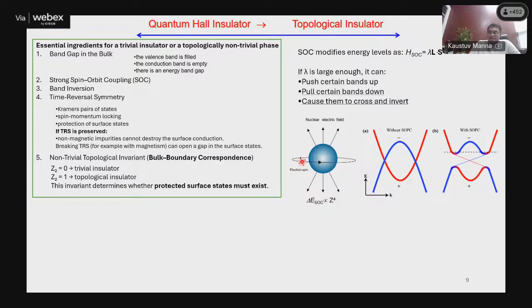So in case of Z very high, in the rest frame of the electron, what you see is that the nucleus is large; heavy nucleus means large Z. So in the rest frame of the electron, you see a large charge which is moving around. It's like sitting on the earth and seeing the sun roaming around. The consequence is that a moving charged particle induces a magnetic field. This is the magnetic field we are using, the internal magnetic field coming from the strong spin orbit coupling, and as you can see, this is proportional to Z to the power 4. That is why for the topological compounds, where we want band inversion, we prefer heavy materials like bismuth, selenium, telluride, compounds where you have large Z.